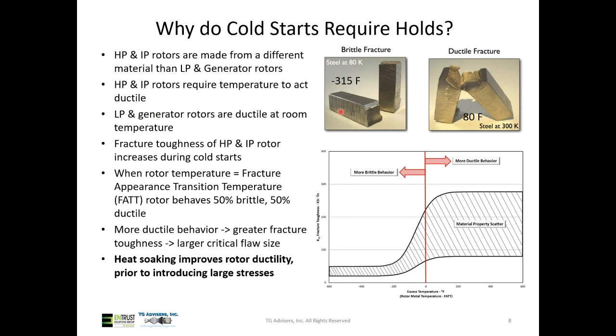So what we have here on the left is a brittle fracture of steel. You can see very cold temperature, 80 K, which is minus 315 Fahrenheit. Our rotor will never get that cold in a steam turbine, but for illustration's sake, what you can see is a very small flaw caused this ultimate failure of the steel bar. So that's known as a brittle fracture, where it doesn't take a large flaw to have this crack reach a critical size and fail, because we have very poor ductility and very, very poor material properties when this material is cold.